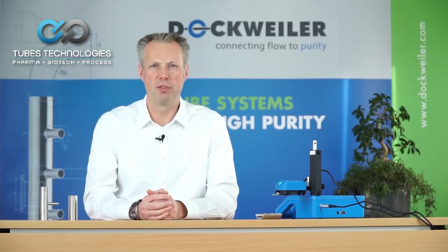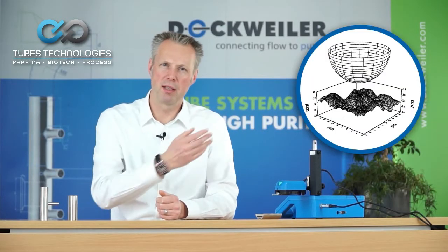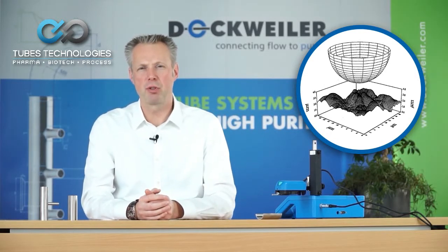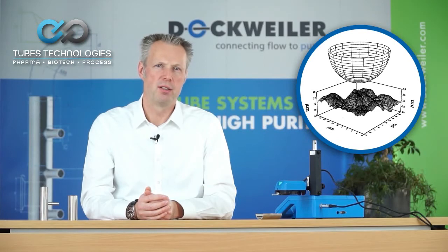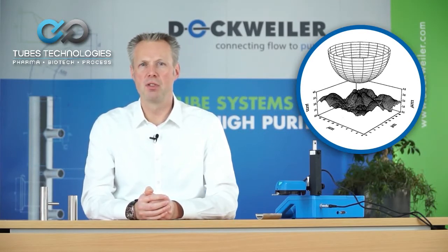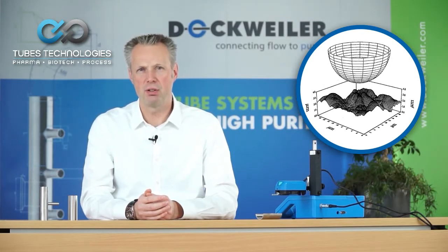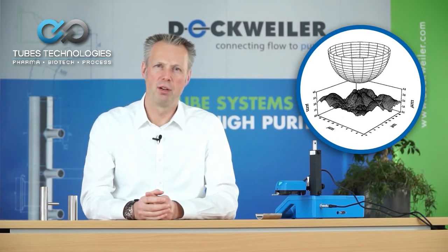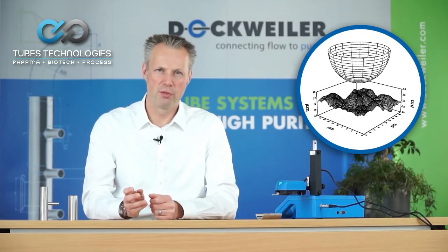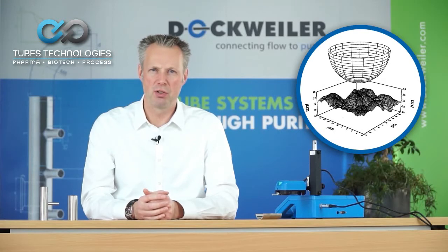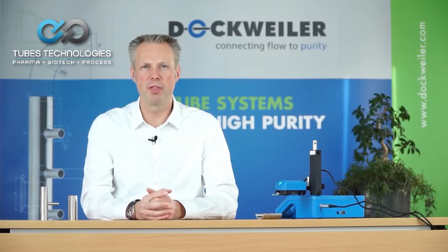But where are the limits of this method? When you take a look at this picture here, it shows you a microscopic picture of the diamond tip needle over a given surface. You can see from this picture that there's certainly a significant difference between the structure of the surface and the size of a diamond tip. So actually it's very difficult to measure the real structure of the surface with this diamond tip.